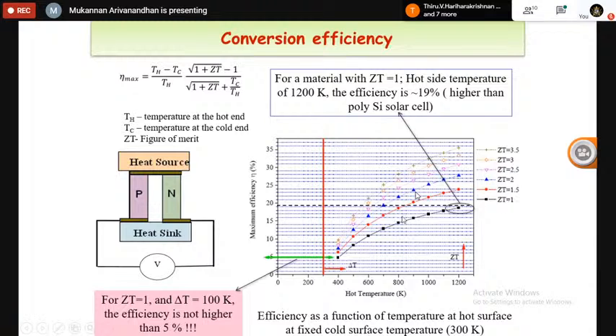On the other hand, if your ZT is very high, even you can realize the same efficiency at half of the temperature, about 600 Kelvin, if the ZT is about 3. Okay, so either by increasing the figure of merit or by increasing the hot end temperature, you can increase the conversion efficiency of these thermoelectric cells.